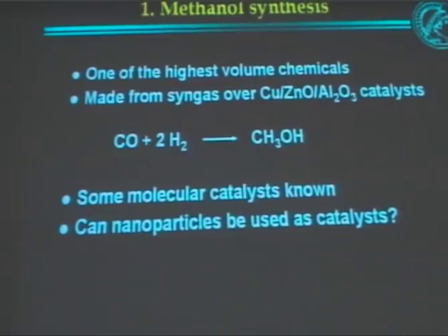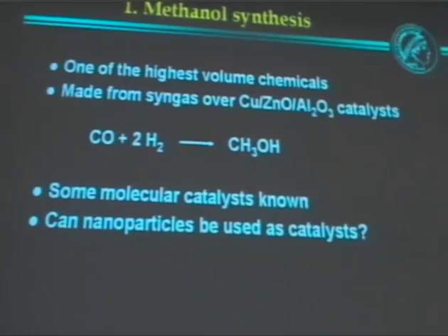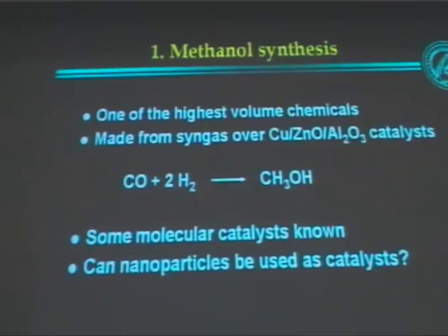There is some belief in the literature that the zinc oxide is important just to create a high dispersion of the copper. And if that's the case, then we should be able to make very high activity catalysts just by making nano-sized copper particles, which also have a very high dispersion. If we can maintain that in the reaction conditions, you'll make a pretty active catalyst without needing this relatively complex composite. Now, the pathway to make copper nanoparticles was introduced by Helmut Bönnemann from our institute